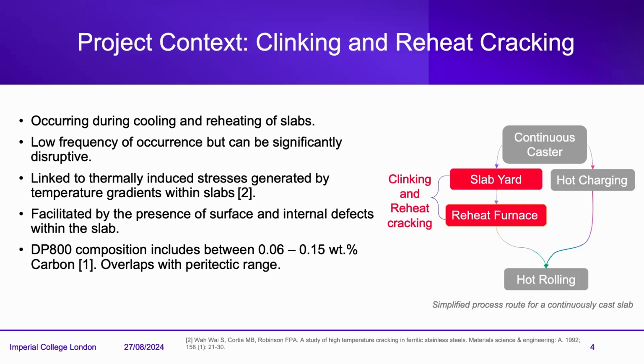There are a number of process routes that a slab can take once it's out of the continuous caster. You can hot charge it and keep it at a temperature above its transition temperature. But clinking and reheat cracking often occurs when it's either cooling down in a slab yard or being reheated in a reheat furnace. It has been shown that clinking and reheat cracking is linked to thermally induced stresses due to non-uniform cooling within the slabs. This has a low frequency of occurrence, about 1 in 1,000 slabs or thereabouts, but when it does happen, it can be quite significant. Another factor to consider is that there are casting defects introduced by continuous casting that can be exacerbated by DP800 steel's composition, which can overlap with the peritectic range.